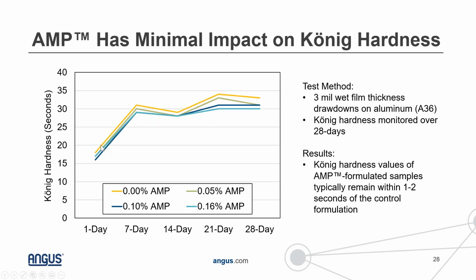And what we find is that there's really not a huge difference between some of these different samples. They all track pretty closely with one another, where we see an improvement to the coating hardness, certainly between the first day and 1 week dry times. And then there's just a very slow increase up to around 28 days. But between different samples, we're getting fairly similar coating hardness values. Usually the samples with AMP are either equivalent or around 1 to 2 seconds softer than the control formulation.